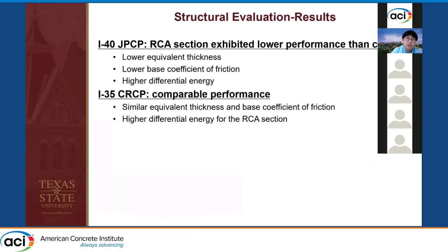So for the results, we found for the I-40 JPCP, the RCA section had lower performance than the control section, which did not have any RCA. We found it has lower equivalent thickness for the RCA section. It has lower base coefficient of friction, and it also has higher differential energy. For the CRCP, however, the RCA section and the control section had very similar performance. We had similar equivalent thickness and base coefficient of friction, but the differential energy was higher for the RCA. Actually, higher differential energy makes sense because the RCA concrete slab has lower modulus, so you have higher deflection, then you will have higher deflection energy.